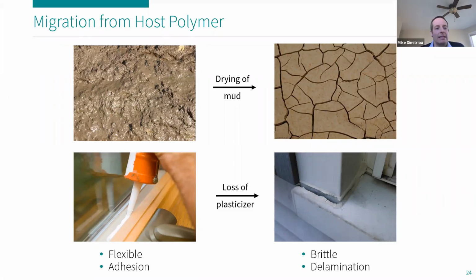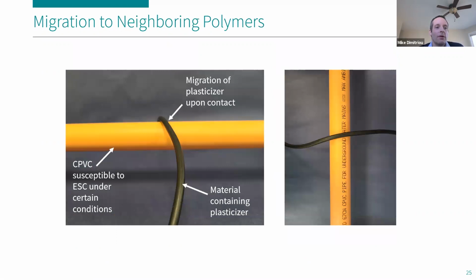A more practical example of this in the construction space might be caulking or sealants. You can see in the bottom left image, there's some caulking that's used to apply to a window joint. It's flowable, but once it dries, it is a material that needs to demonstrate a certain amount of flexibility and adhere to those substrates. However, over time, if that plasticizer leaves the sealant, you could end up in a situation where it embrittles, it possibly delaminates, and it no longer serves its function of filling in and sealing that gap. So this was an example of what happens to your host polymer when plasticizer leaves it. The other side of the equation is, where is the plasticizer going?